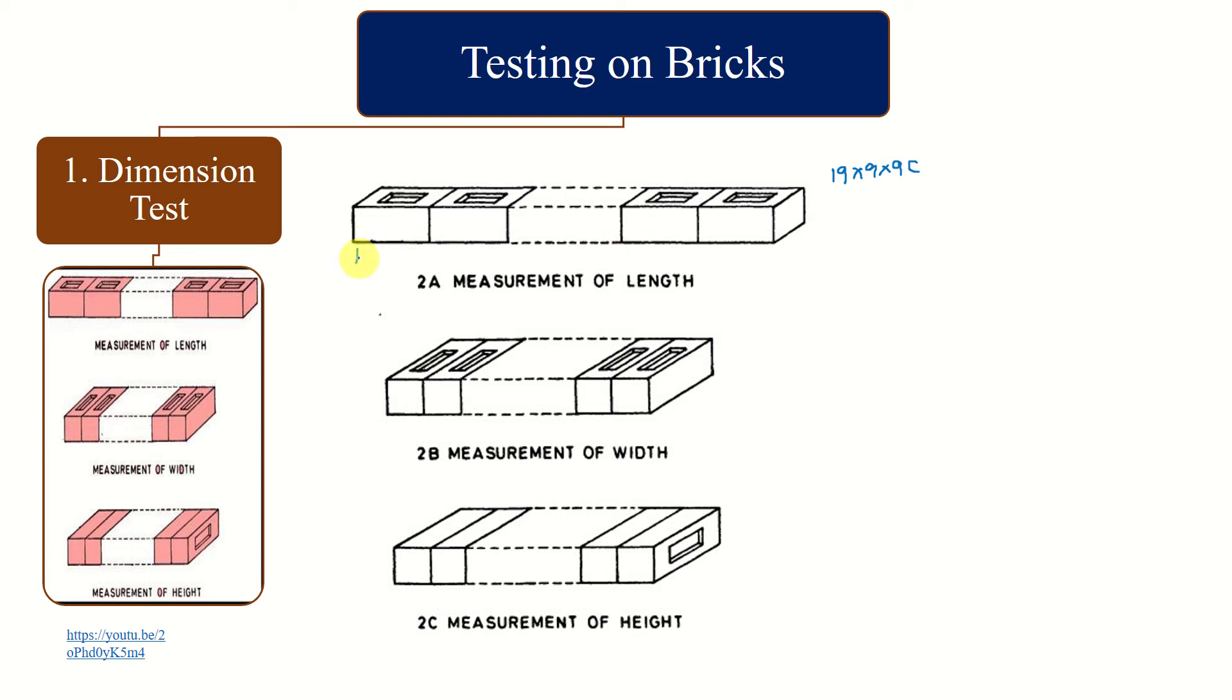20 bricks are placed longitudinally and the overall length is measured and compared with the theoretical length, that is 19 multiplied by 20 because every brick measures 19 cm length. So that is 380 cm.